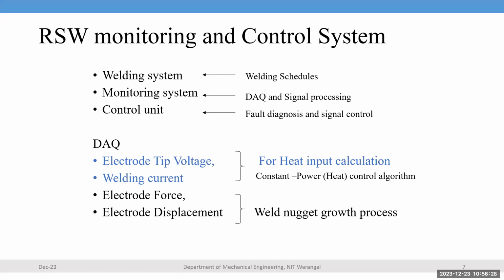The electrode tip voltage and current give how much heat input there is during the process. If you apply less heat than required, the weld nugget is not formed. If it is more than that, expulsion takes place during the process. So these are the two bad effects: low and high heat input result in no nugget formation as well as expulsion. Due to that, the weld fails.